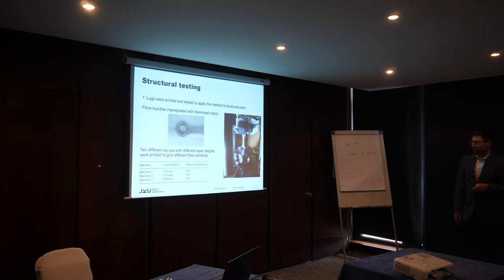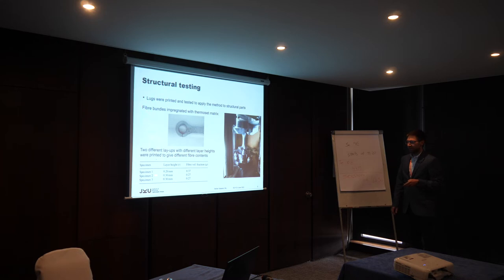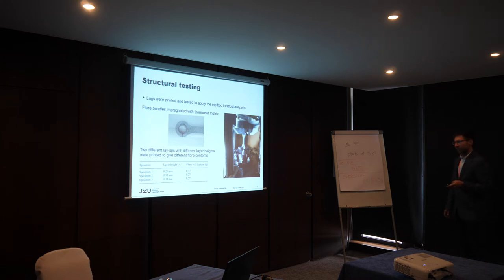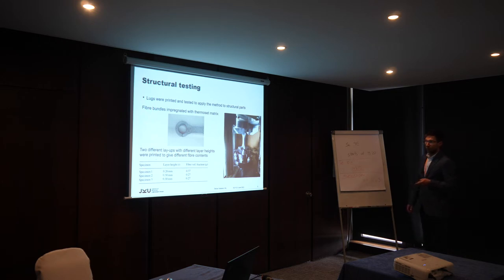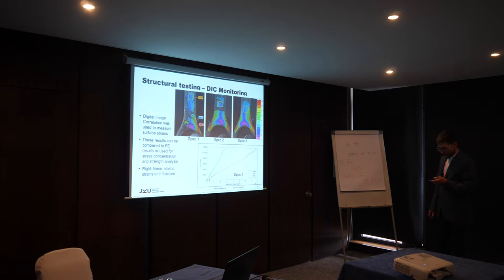Unfortunately, because of lack of material, we only have three specimens. Specimens two and three in our study are made with the standard material and printing parameters of Isoprint, giving a fiber volume fraction of about 27%. Specimen one we experimented with by decreasing the layer height to obtain a higher fiber volume fraction.